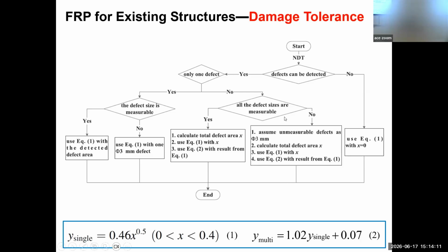This procedure can be coded. You can use MATLAB or Python for automatic calculation - you don't have to do it manually. What you need to do is work out the theoretical capacity of the interface, then go to the site, use NDT to check the defects, input the defect size into this coding procedure, and work out the reduction factor.